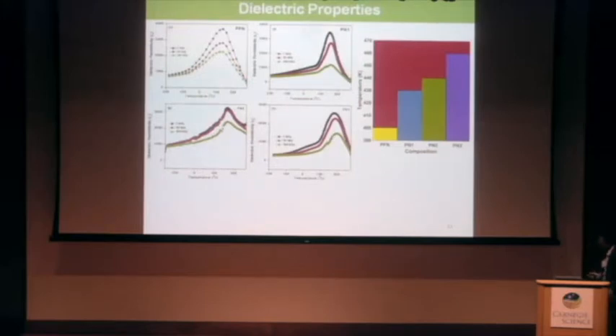This is the dielectric property, to probe the ferroelectric phase transition of all the composite structures. This is the dielectric spectra of PFN, PN1, PN2, and PN3. As the magnetic content increases, the ferroelectric phase transition temperature, Tc, goes on increasing, and all these compositions show relaxor behavior. With increasing magnetic content, for PFN it is around 400 Kelvin, for PN1 around 430, for PN2 around 440, and for PN3 the ferroelectric phase transition is around 460 Kelvin.